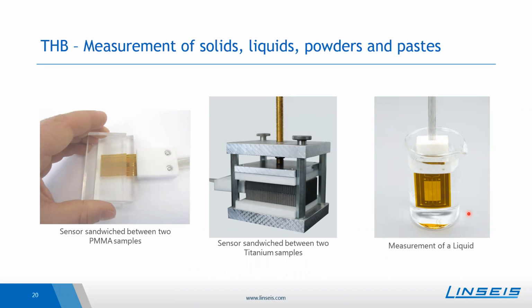The second question there was, how do you measure the thermoconductivity of a liquid sample in a temperature range, for example, from 10 to 100 degrees Celsius? So the THB can easily adapt it into an already existing furnace. For example, in the lab, we also have a drying furnace where you just can put in the sensor and the beaker to be able to realize measurements, or as seen in one of the application examples, one can, for example, also use a tempered liquid bath where you just put in the beaker with the sensor.